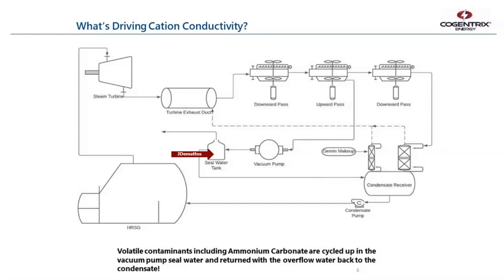The overflow water from the seal tank, since this plant does not have any wastewater discharge capabilities, all this seal water is recovered and pumped back into the condensate receiver with the rest of the condensate. So the water coming out of the seal water tank is about 1,000 to 2,000 conductivity. We believe that's mostly ammonium carbonate. We have done a couple of samples and we've verified that there's not a lot of organics. We don't have sodium, we don't have fluorides.